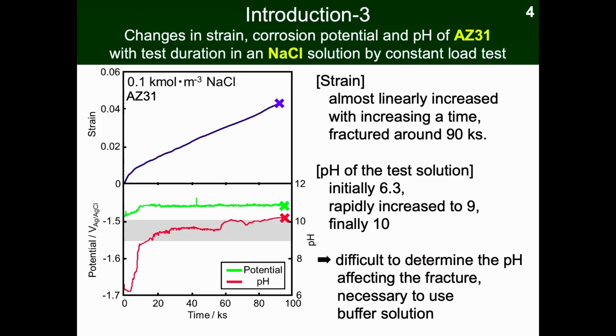This is the first research of the environmental assisted cracking of the AZ31 magnesium alloy in the sodium chloride solution, using a constant load test. Here is a change in the strain, corrosion potential, and pH with the testing time. You can see the strain almost linearly increased with time and fractured at about 90 kiloseconds.